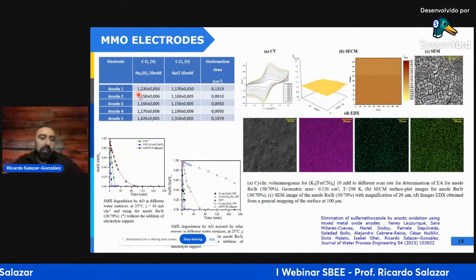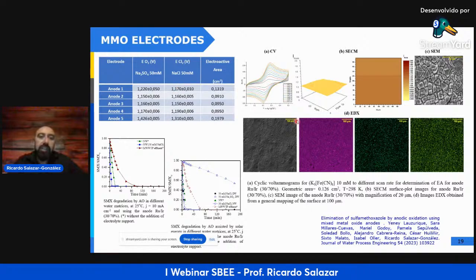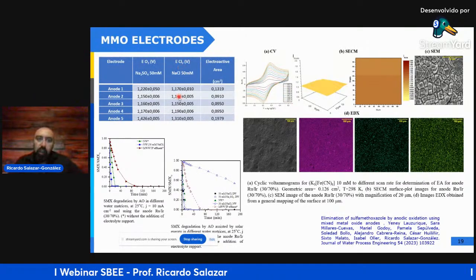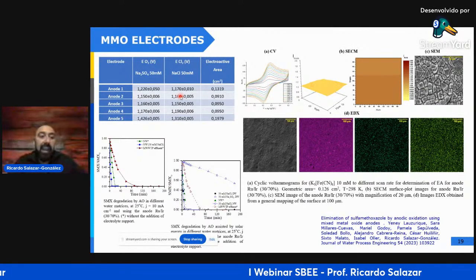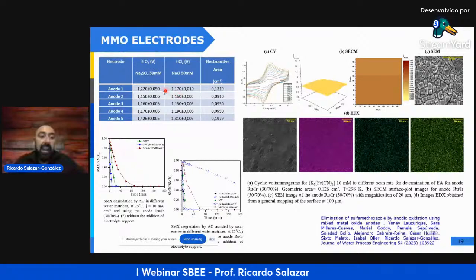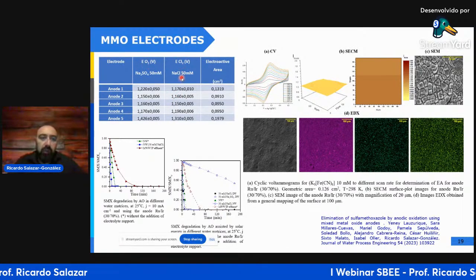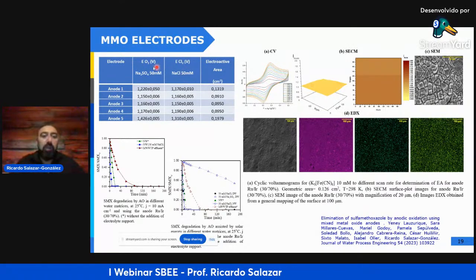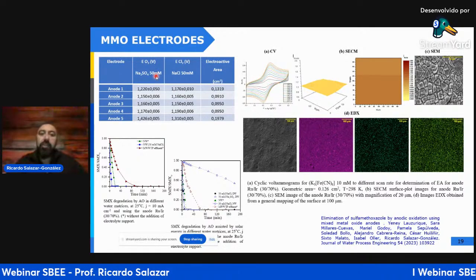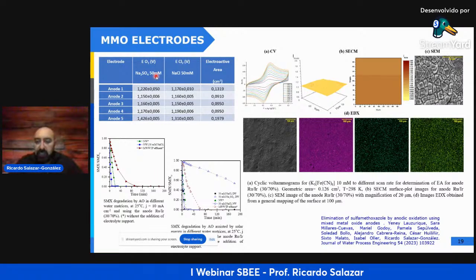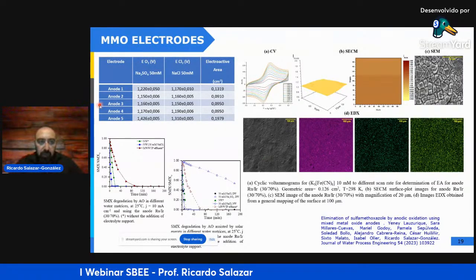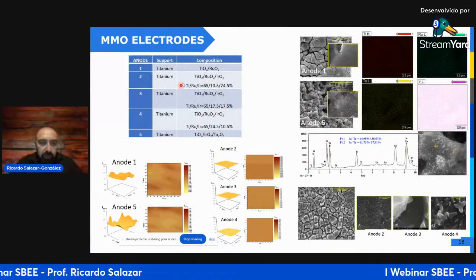This kind of electrode produces a high concentration of chloride in the solution, and the presence of chloride produces hypochlorite, and they have a lower overpotential for the evolution of oxygen and chlorine, unlike BDD electrodes, where the overpotential is higher. And you can see the presence of different oxides with respect to this kind of electrodes with this composition.